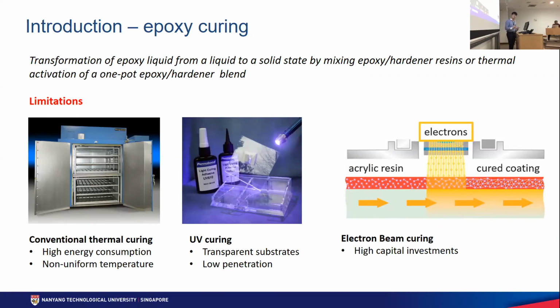For the introduction, epoxy curing involves the transformation of epoxy liquid into a solid state by mixing epoxy and hardener resins or the thermal activation of these epoxy hardener blends. Curing methods impose several limitations. For example, conventional thermal curing requires a lot of energy and can lead to non-uniform temperature profiles between the substrate and the adhesive. UV curing is limited to transparent substrates and has low penetration depth.